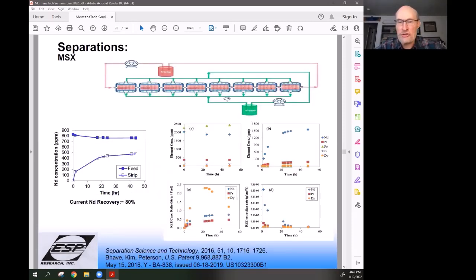You can then also hook these units up both in parallel and/or in series to give you very efficient collection of material. Shown on the left side, the current neodymium recovery, for example, is over 80%, and the kinetics are incredibly fast. We've achieved that in less than an hour, coming to equilibrium and pushing it up to 80–85% recovery. The kinetics of the capture are very, very fast, shown on the left side of the 4 diagrams on the right. And on the far right side, you can see the release kinetics are pretty reasonable. So we get the materials in, we get them across the membrane, and we get them out pretty quickly.